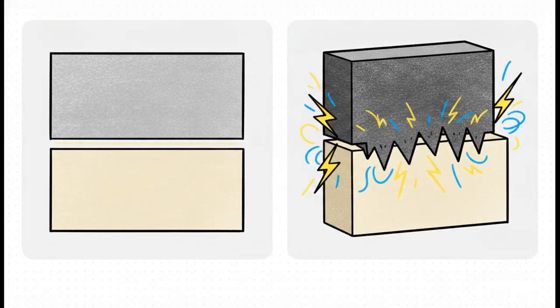Now, a bare piece of ceramic doesn't do much good in an electronic circuit. We have to figure out how to attach metal to it. The older, mature technology is direct bond copper, or DBC. But for extreme performance, we rely on active metal brazing, or AMB. This uses reactive metals, like titanium, to chemically bite right into the ceramic, creating a wildly strong bond. This AMB technology on an aluminum nitride substrate is the exact reason your electric vehicle can fast charge in 20 minutes. It handles the extreme thermal cycling of the EV's inverter without ripping itself apart or melting.